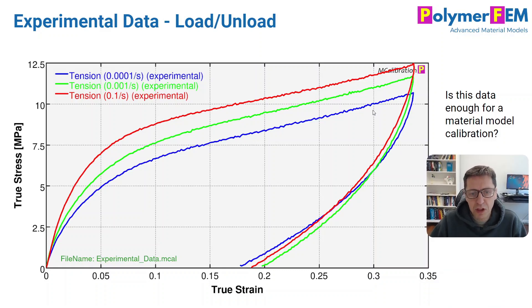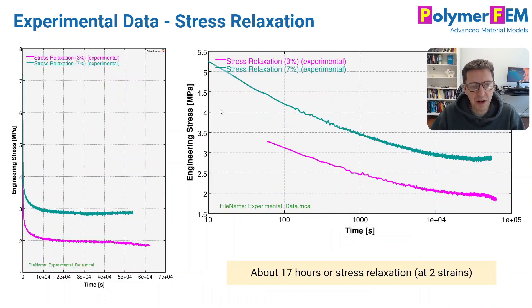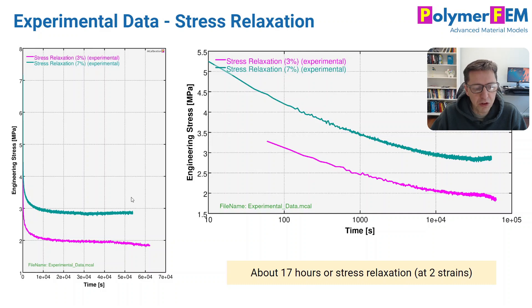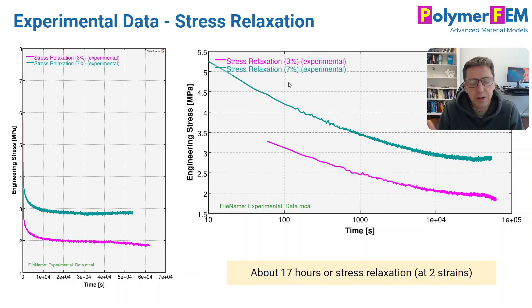But I also did more. I tested the same material in uniaxial tension to either 3% or 7% strain and then held that strain constant for a pretty long time, about 17 hours. Here's the data: the figure to the left is stress versus time, and the figure to the right is stress versus logarithmic time. This is the data that I want to use.